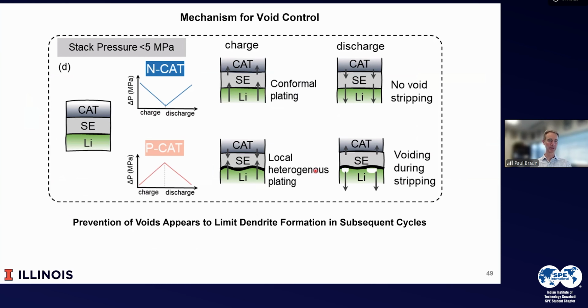And so basically what is happening is at low stack pressure, when I'm charging the battery, the lithium's getting bigger and the cathode is shrinking, so that the two sides are working together. During discharge, as the lithium gets smaller, the cathode gets bigger. On the other hand, if I don't control the stresses, they fight each other. During charge, they're compressing. That's probably okay. But then during discharge, the cathode is pulling one way and the lithium's pulling the other way, and voids form. And these voids lead to failure.